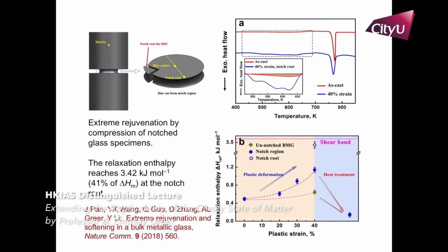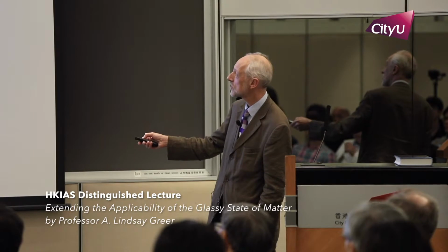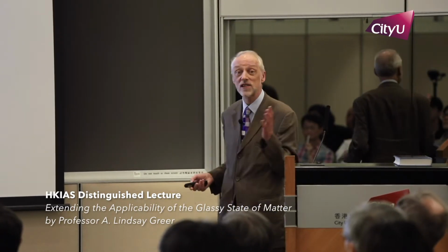So here's what the sample really looks like. Here's your notch. So we compress it, then we cut out the disk and then cut out the edge of it, put it in a calorimeter, measure the stored energy, and you find it's enormous. It's very near the energy that is presumed to exist inside a single shear band, except here it now exists throughout the material. And the energy stored in this material, which is released when you warm it up in the calorimeter, is about 40% of the heat of melting. So you've moved it to quite a different glassy state.